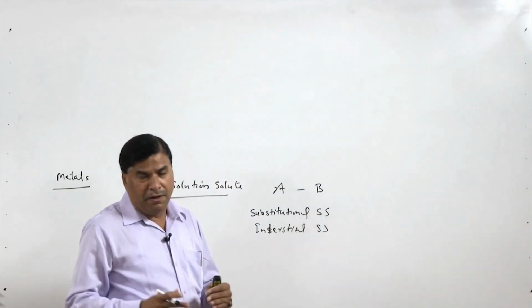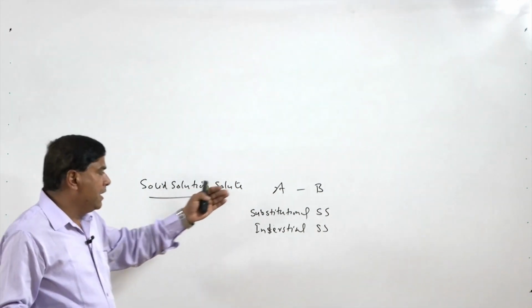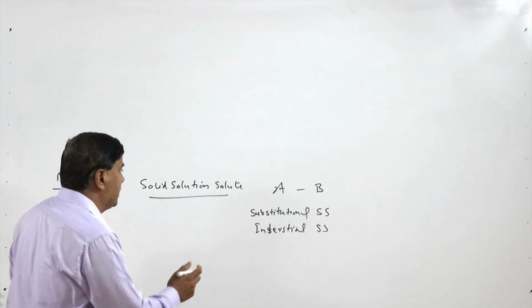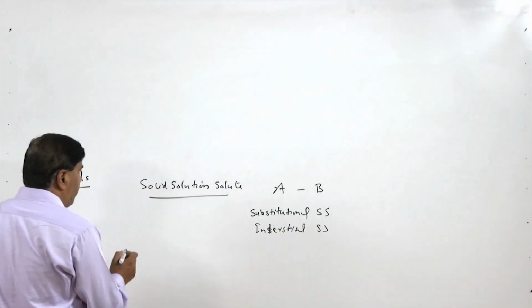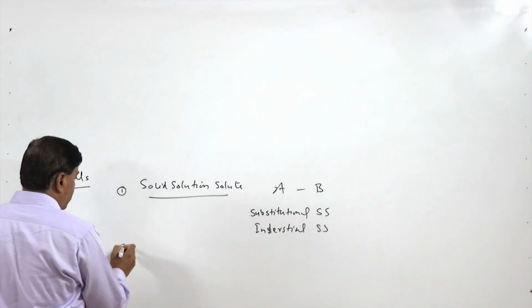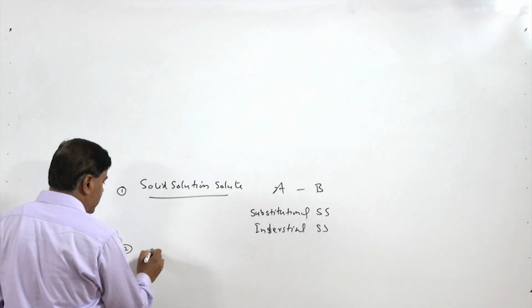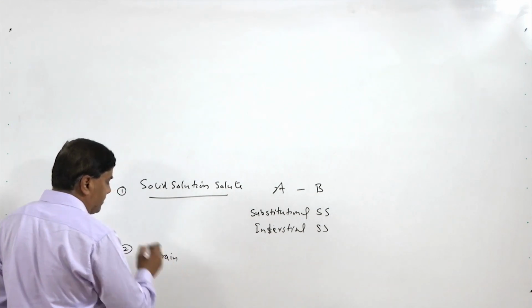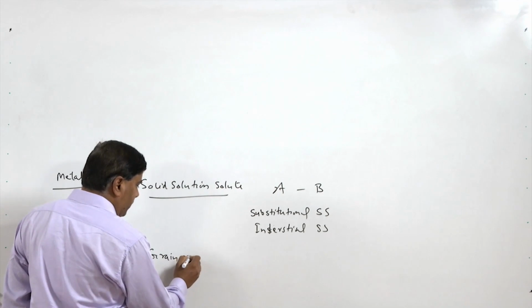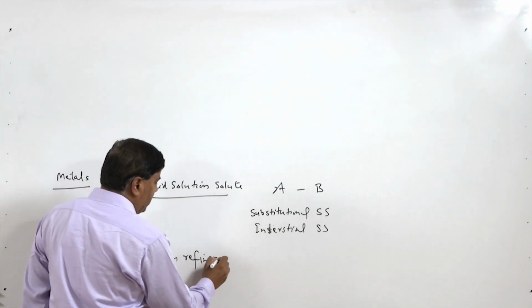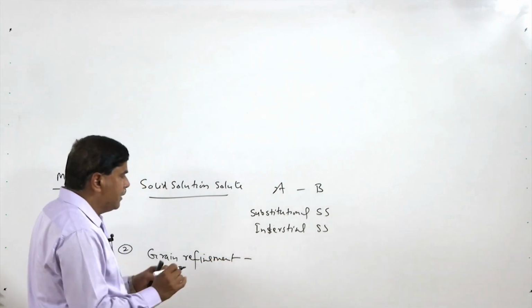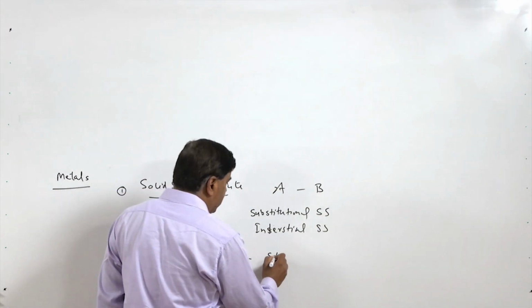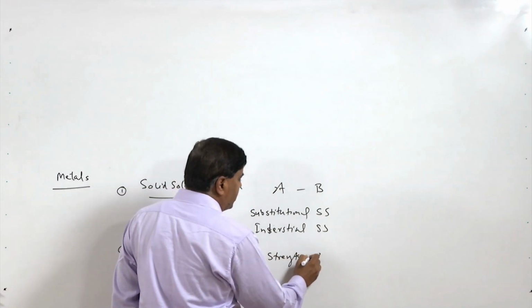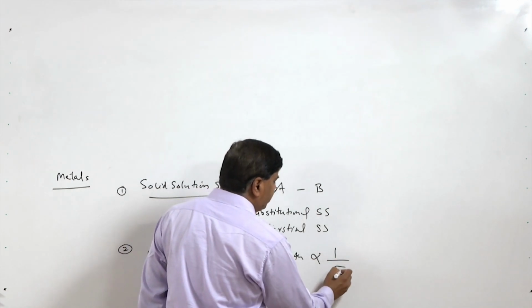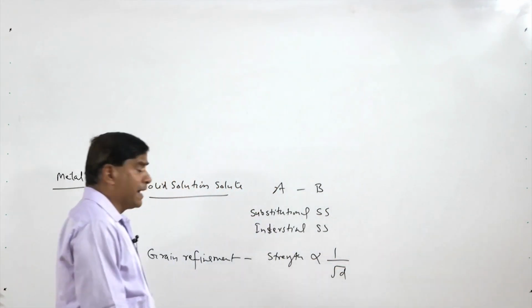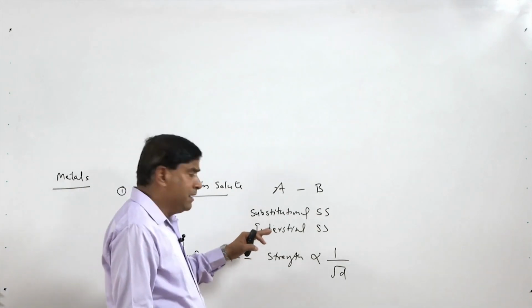Interstitial solid solution results in much higher strength with the addition of the solute as compared to the substitutional solid solution. Then another mechanism, and this is the commonly used one, is grain refinement. The metal systems are also strengthened by grain refinement. And here the strength or the hardness is found to be inversely proportional to the square root of the grain size. Finer the grain, higher is the strength.